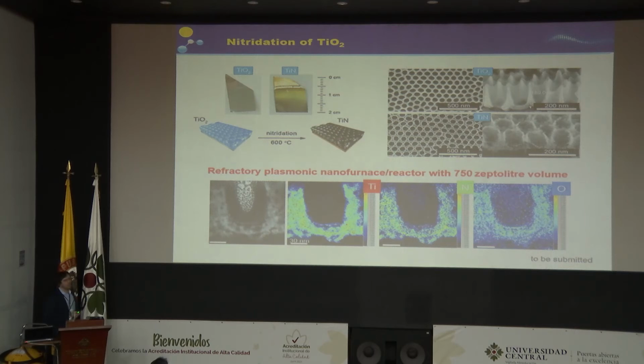So basically, we put a titanium metal foil inside an electrolyte, and through corrosion we create self-assembled nanocavities, which create a hexagonal lattice in the material, and these are created centimeter long, very regularly along our metal foils. Here you can see a cross-section and also high resolution TEM mapping of a lamella of our material. This is titanium oxide, this is titanium nitride after nitridation. We create really small cavities of 80 nanometers in aperture and 150 to 200 nanometers in length. As you can see, these are really very small nanostructures that, of course, can sustain surface plasmons.